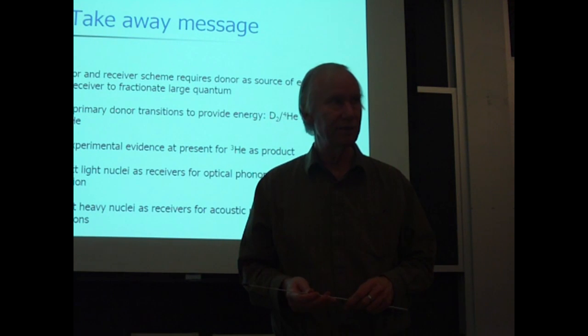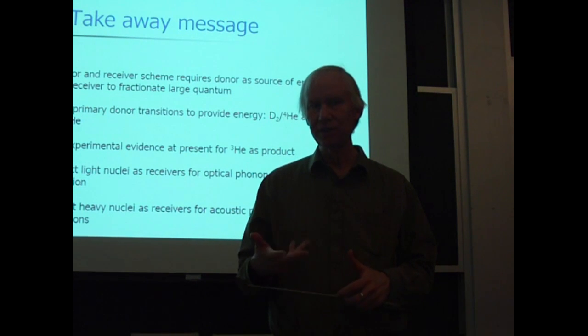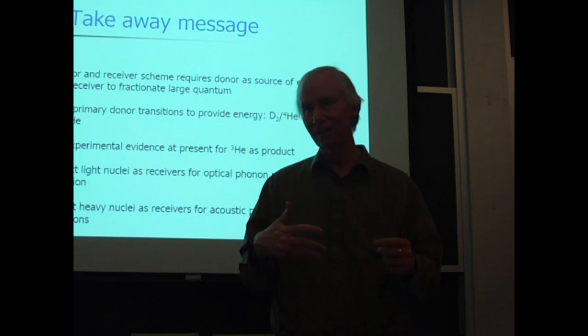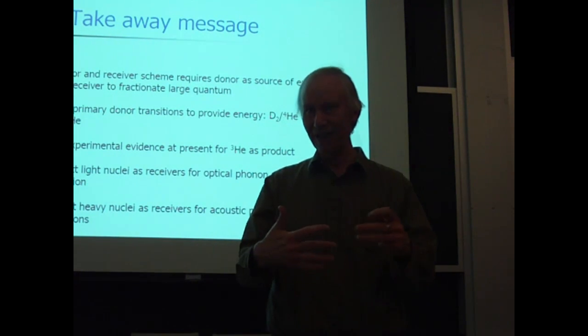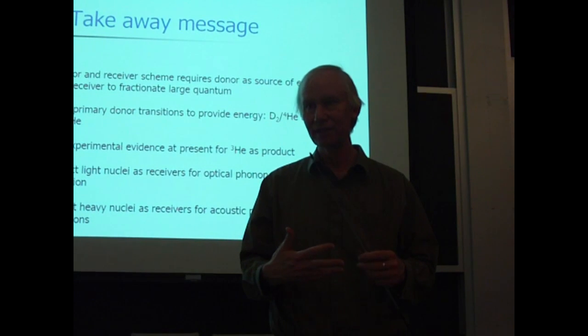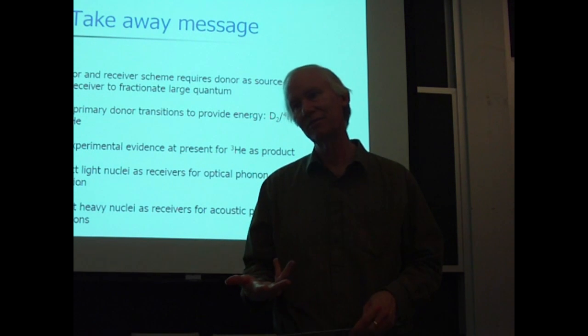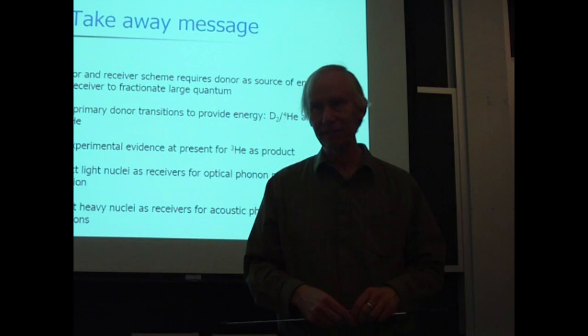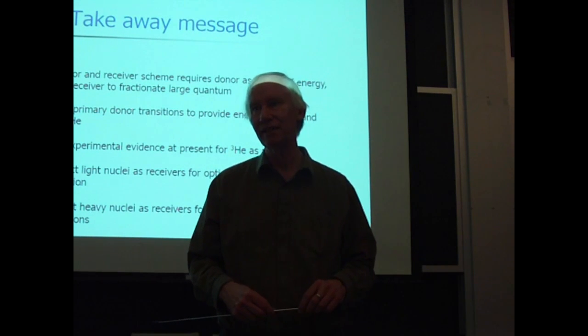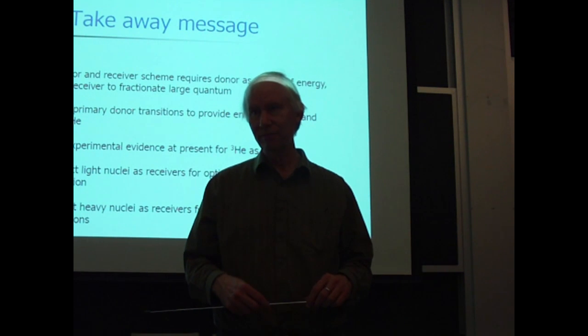I think there are issues with respect to low solubility. If you have acoustic mode operation, you put your energy in the nickel, it disintegrates in your nickel, so your lattice has problems. So you might expect degradation of the lattice itself. So there may be other material science related reasons that might have to do with the difficulties involved. I mean, Piantelli sees excess heat from nickel deuterium, but it's at a much smaller level than for nickel hydrogen, for example.